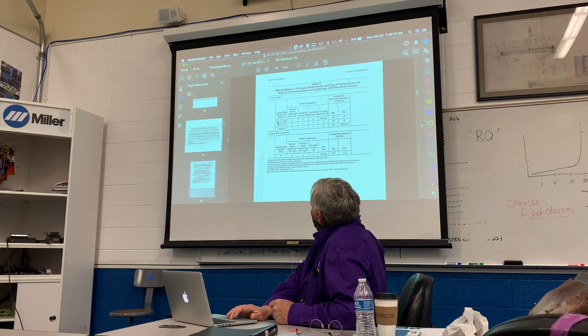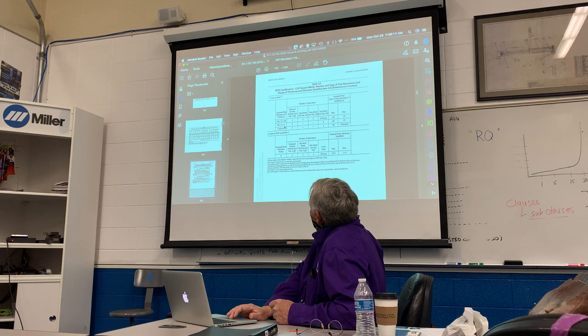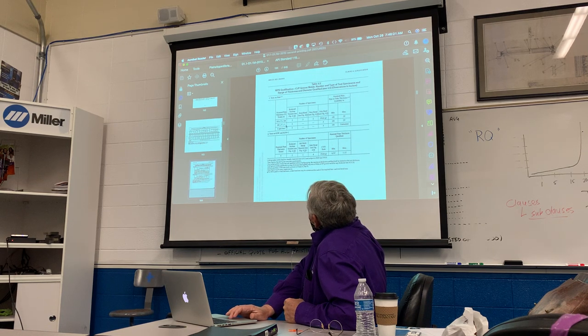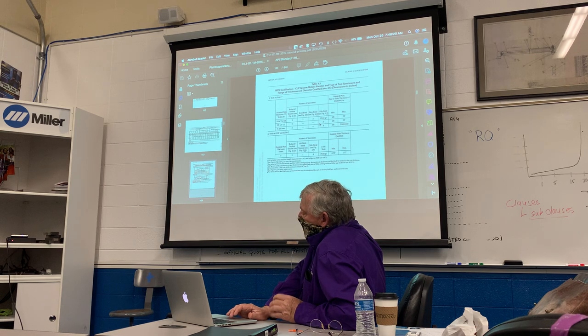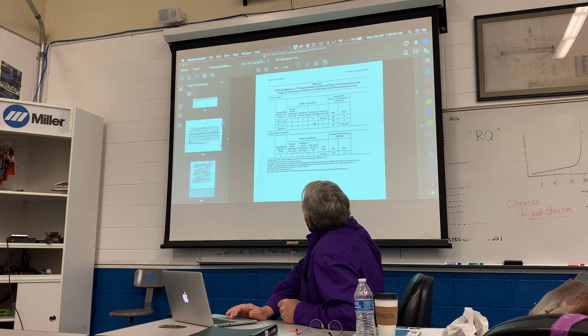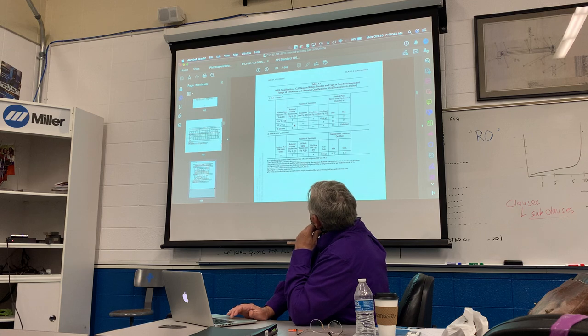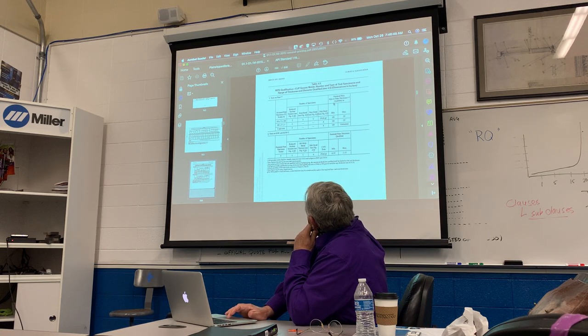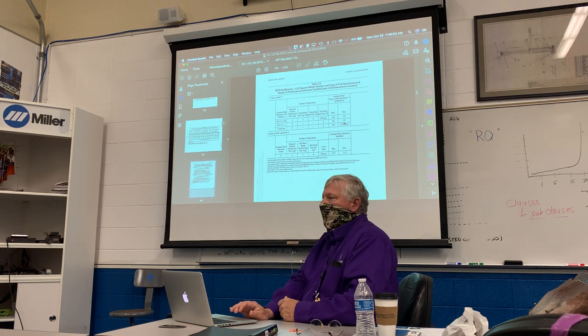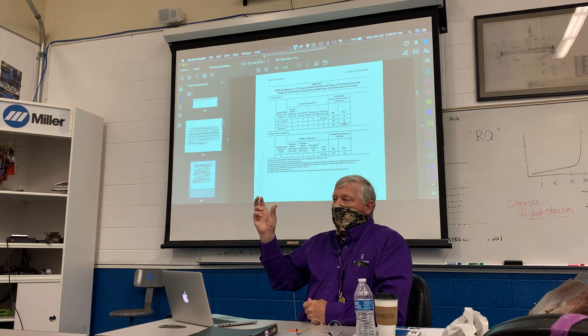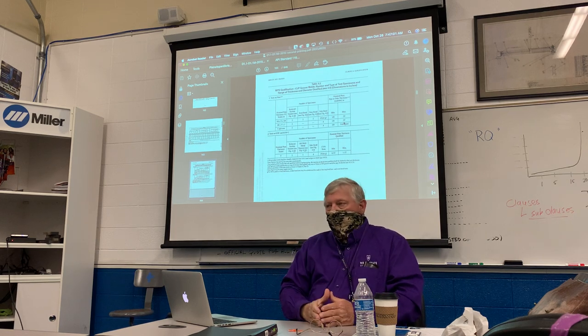If it's a thicker test, T is between three-eighths and one inch. This is your minimum for the range, this is your maximum, and so on. So if you're doing a half-inch test, you pull two reduced-section tensiles and four side bends. If that procedure test passes — all four side bends are good and the reduced-section tensiles are at or above the tensile strength of the material — the procedure is qualified. Notice it's one-eighth minimum and 2T for the thickness, so you're good up to one inch on a half-inch test, but in all cases for D1.1 one-eighth is going to be the minimum.